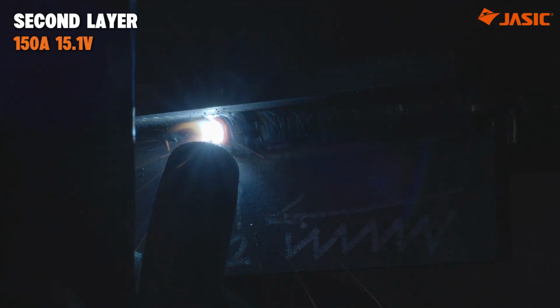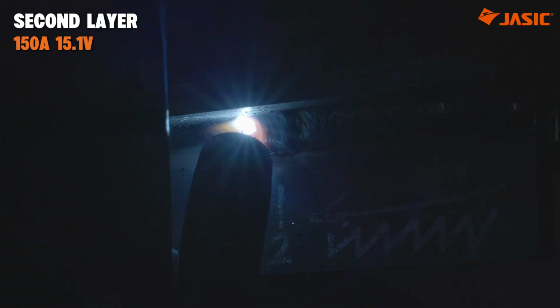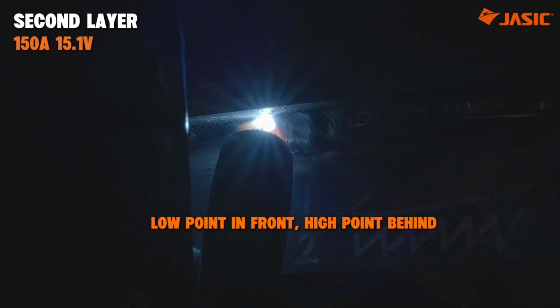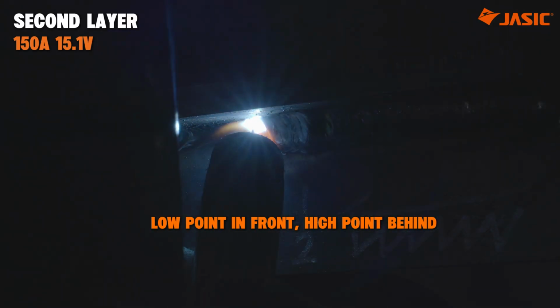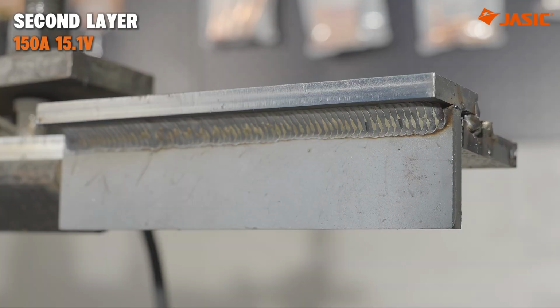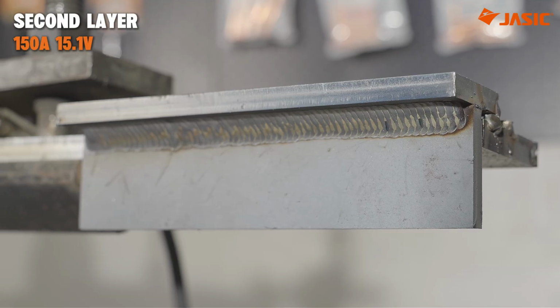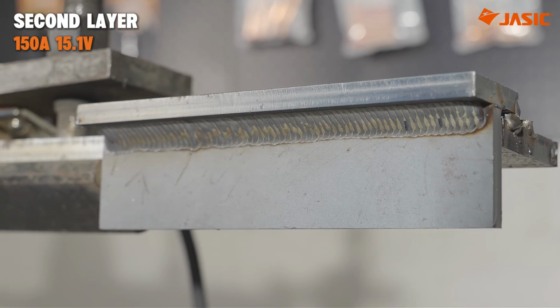Don't travel too fast. The second layer needs to completely cover the first pass. Remember, low point in front, high point behind, and every movement should reach the upper edge of the molten pool. By combining the zigzag movement with the downward gun angle, you help push the molten metal upward and counteract the effect of gravity.